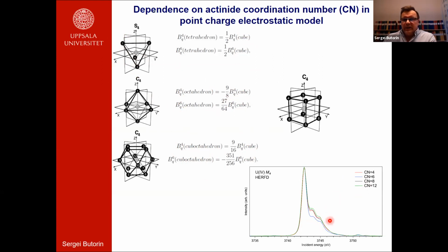You can see that, indeed, there is a dependence on the coordination number, but there is no trend. So we go from CN4 down to CN6 and then back to CN4, and then the intensity of this shoulder is a little bit higher for CN12. And when I did the calculations for another ion, uranium 3+, the behavior was very different. So unfortunately, one can't establish any trend in the dependence on the coordination number, but the spectra do change.